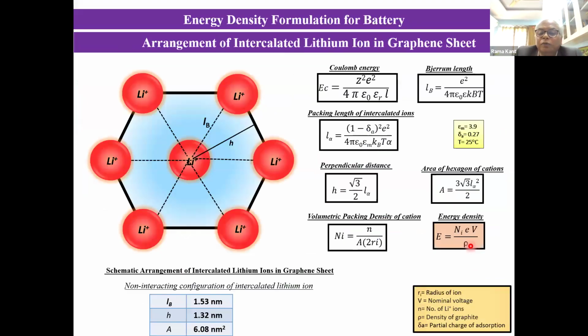And now we want to see how to pack this lithium into my graphene interlayer. So here there is a concept of Zerum length, or Bjerrum length actually. Bjerrum length is where the Coulombic interaction energy becomes equal to the thermal energy kBT. The distance at which two interacting ions or charges have that much energy is called the Bjerrum length. And this basically depends on the dielectric of that medium. Here, the dielectric of this medium is the dielectric of my graphene layer itself, and thermal energy. So you put in this number and the fraction of charge which is lost on lithium due to adsorption, that is delta A.